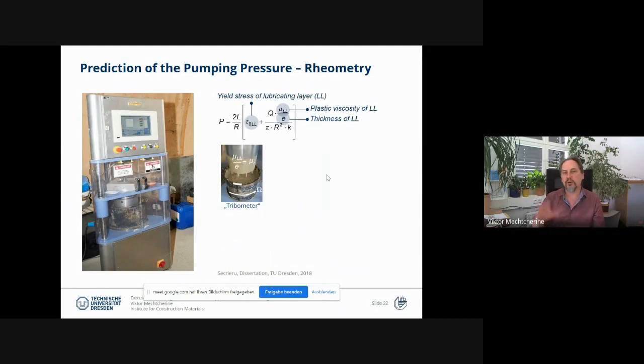decades ago already. So this upper formula is valid for relatively stiff concrete, and two material parameters we need to define are the yield stress and plastic viscosity, but not of the concrete, but of the lubricating layer, this thin layer on the wall. So how to derive these parameters? We can perform experiments like this using a smooth cylinder instead of other geometries which are usual in testing rheological parameters of concrete. In this case, a really smooth surface is essential. So we call it kind of a tribometer.